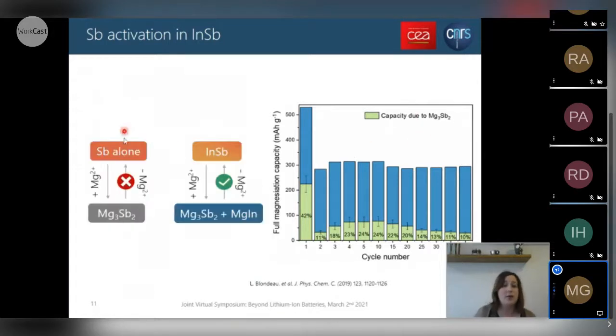So to sum up, when in literature you look at the reactivity of antimony alone, Mg2+ can be inserted in the structure, but it's too stable for the Mg2+ to be extracted. But when antimony is combined with indium, the Mg3Sb2 phase seems to be formed, and we can also partially remove Mg2+ from this phase.